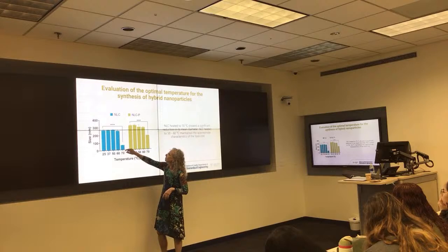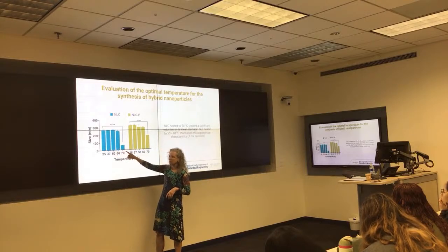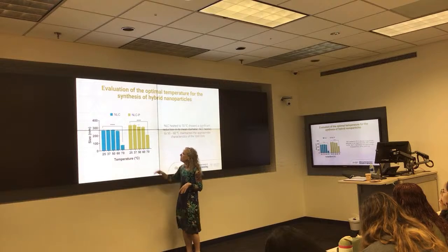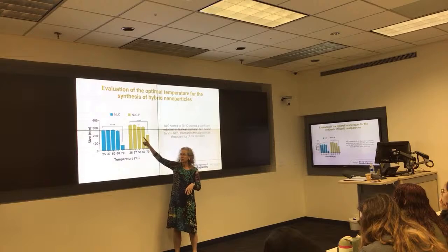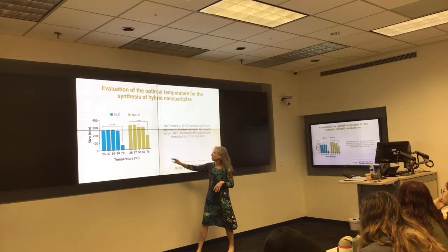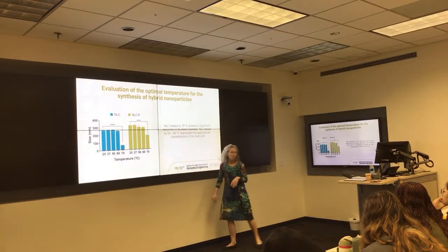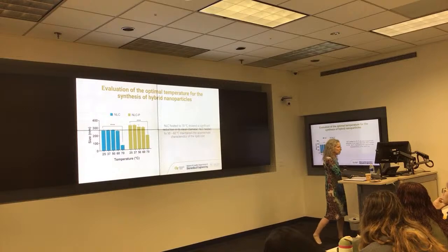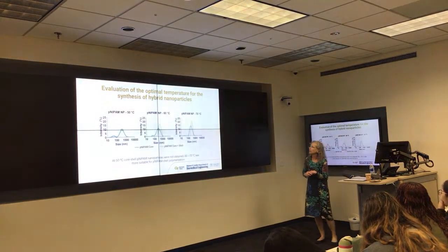And what we found was really 50 degrees was ideal. They start to melt at 60, but they really melt at 70, so we can't go there. As she puts her drug in there, you see this a little bit more, right? They're a little less stable even at 60 degrees, and certainly unstable at 70 degrees, although ironically a little more stable than they were without the drug. And so then she said, okay, well, at what temperature can I make the polyNIPAM?